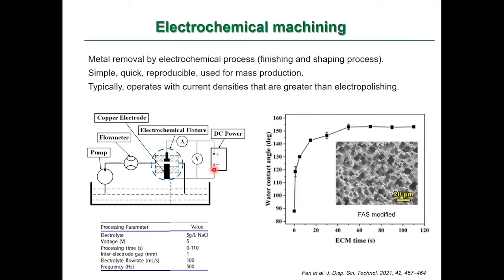So electrochemical machining is a type of electrochemical polishing step where they use different setups and closer electrodes, maybe the anode moving to the cathode. It is usually for mass production, a metal removal anodic process, and it typically operates at higher current densities. This image shows how the contact angle varies with the machining time for a steel surface. You can see the surface machined, removing the metals, and that itself with the modification will make the surface superhydrophobic.